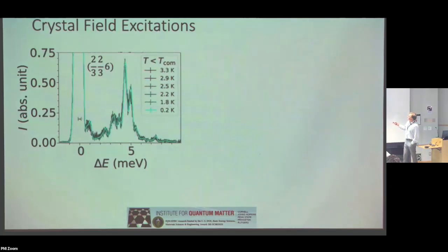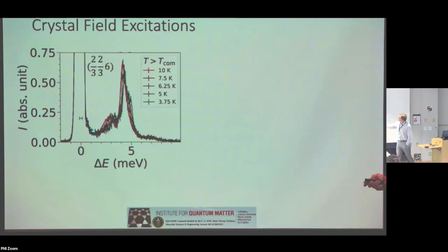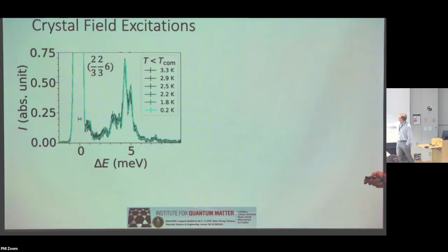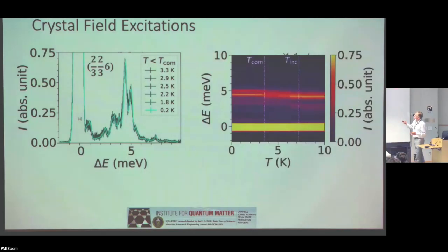But then when we go into the commensurate state, then actually we get quite a few additional little peaks showing up. And this whole kind of spectrum that seems to be present here, this kind of distributed stuff, actually becomes weaker, and then intensity kind of collects into specific peaks. And then what's happening there is really quite interesting. It's laid out here a bit more. So this is the paramagnetic state, and that's the main peak, and then this is the weaker peak here. And then you get into the incommensurate state, and it's still kind of fuzzy. And then finally, when you come to low temperature, then it breaks out in kind of sharp levels.